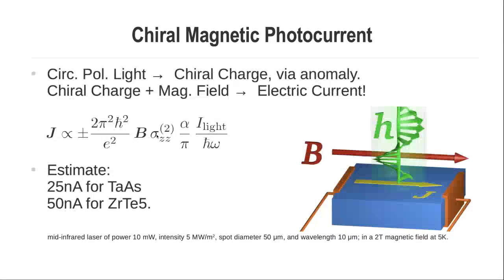Yes. So the reason why conductivity doesn't get into this expression is because of the following. We assume that the entirety of the light that is falling on the crystal is getting absorbed by the crystal. So if the light is going to get absorbed in 100 nanometers, this current will be distributed across that 100 nanometers depth. If the light is getting absorbed in 5 nanometers, this current will get distributed in that 5 nanometers depth. Is it not a current density in your formula?